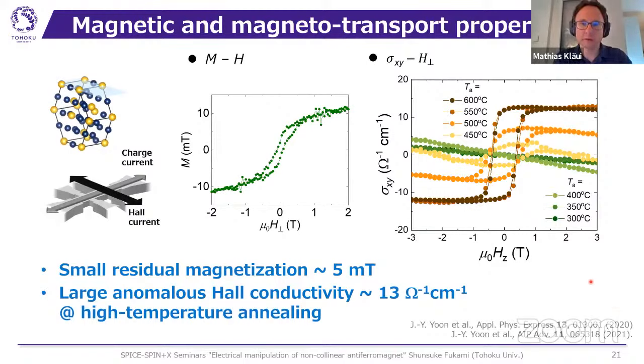Before Dong-Wook asks, maybe I have a follow-up, Shunsuke. If the 240 nanometers does not depend on some structural length scale, what sets the domain size then? Yeah, that's a very interesting point, because for ferromagnetic systems, the domain size should be determined by the competition between the exchange and the magnetostatic dipolar energy. But for the antiferromagnet, there should be no dipolar field. So that's a very interesting issue, and we would like to clarify it.